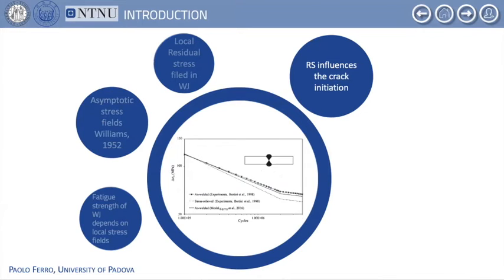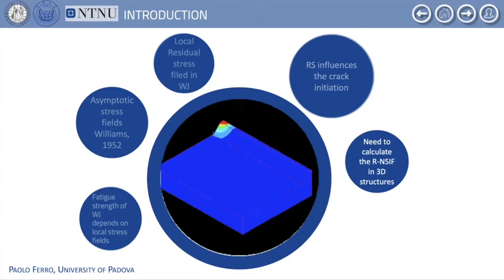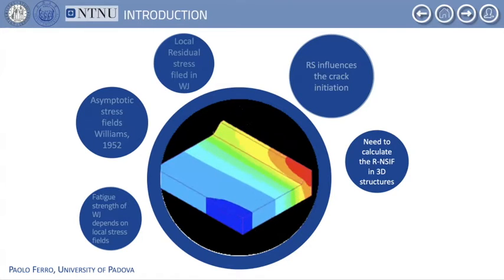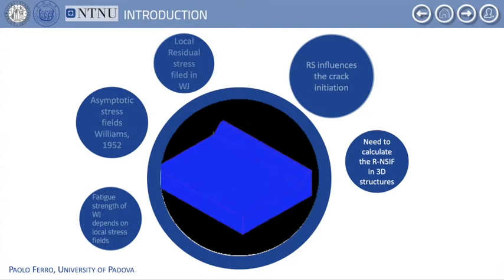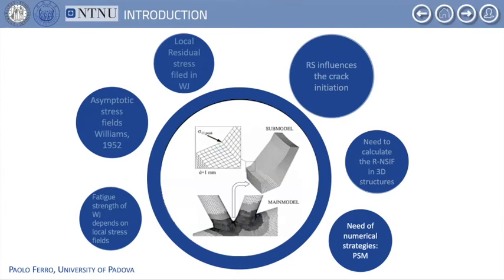Now, the residual stress influences the crack initiation in the high cycle fatigue regime, where plastic effects can be neglected. For this reason, it is very important to assess the parameter that quantifies the intensity of the singular residual stress field, called the residual notch stress intensity factor, in particular using 3D numerical models and therefore capturing boundary effects.